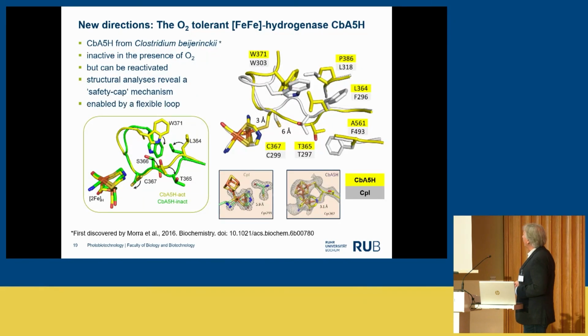And the reason for that we found out is because you have a protection by an amino acid. This is a cysteine here. This protects this distal iron. So again, you have the control of the model enzyme, and you see that there is no cap. We called it safety cap mechanism. So there is no cap that this cysteine can protect the active cluster. In the case of the CbA5H, the oxygen-tolerant enzyme, you recognize that you have a protection of this cluster under oxygen. Still, it's not active under oxygen, but it's protected.